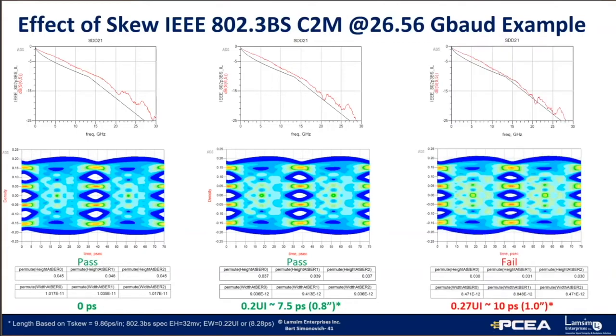When we add only 2.5 more picoseconds of skew, the insertion loss fails the insertion loss mask at 21 gigahertz, and the resulting eye height just fails the 32 millivolt spec. Now, if the measured loss happened to line up exactly on the insertion loss mask with no skew, the eye height would most likely have failed with 0.2 UI of skew budget. This suggests the skew budget may be insufficient for PAM4 signaling. And remember, 0.2 UI was total skew budget from all sources. So we would need to reduce the fiber weave effect skew even further.